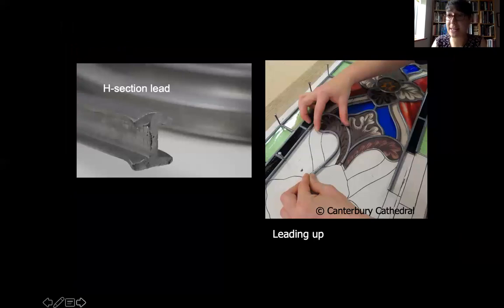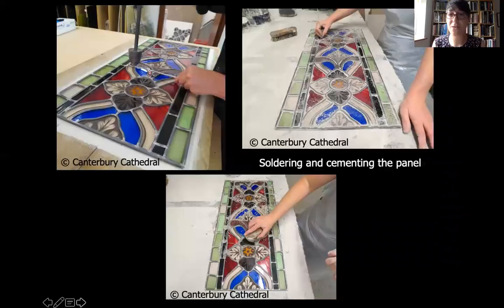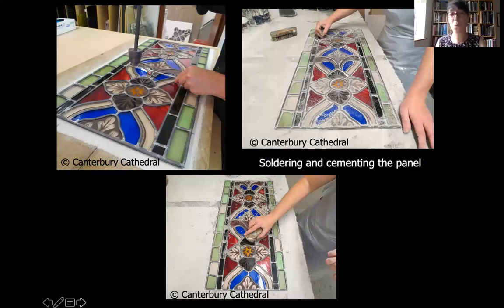Once the glass has been painted in its individual pieces and fired in the kiln, it's brought out and laid onto that cartoon for leading up. Most glass windows are held together with lead cast or milled into an H-section - more accurately like a capital I with two grooves on either side that the glass fits neatly into. Lead is bendy so you can bend it around each piece, then the joints where the lead lines meet are soldered to form a panel. Finally the gaps are cemented and sealed.